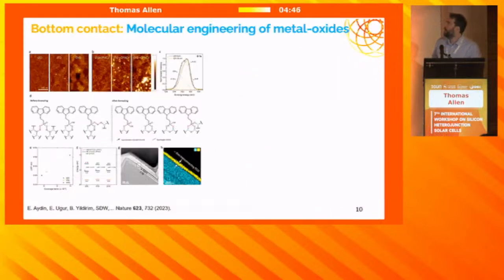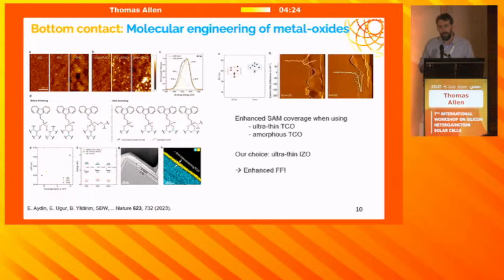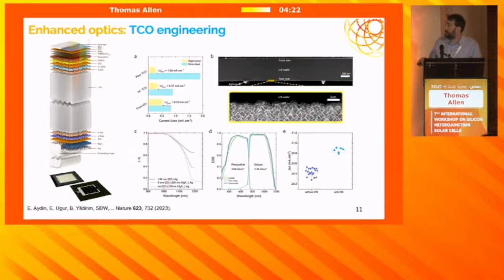Okay, so now we're going back to tandems and back to perovskites. So we found an optimum for anchoring the SAMs onto IZO. We think that's largely due to the amorphous nature of the IZO and the fact that you then get better coverage of the SAM on the IZO layer. And so with that kind of optimization, we were able to improve the fill factors in the tandems. And then, as I said, our initial batch of tandems were optically pretty poor. Now you can see a much better improvement just visually.